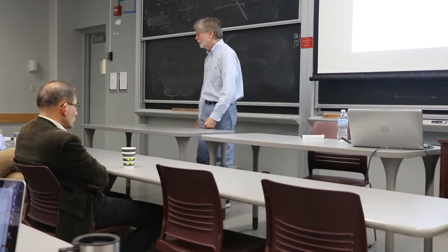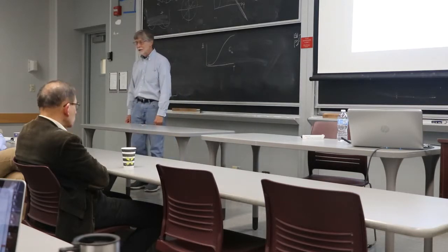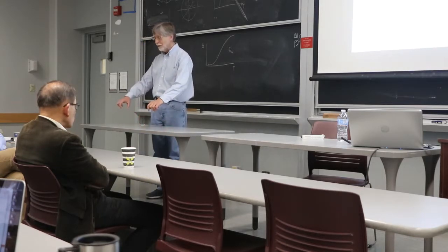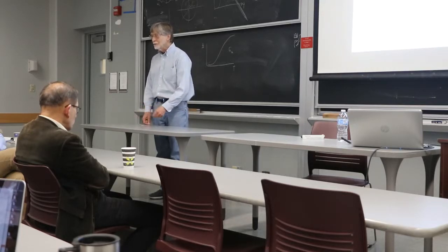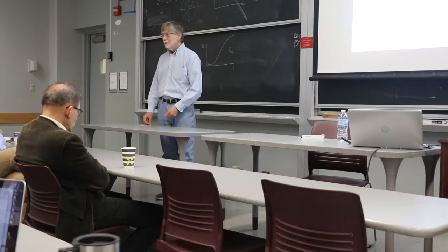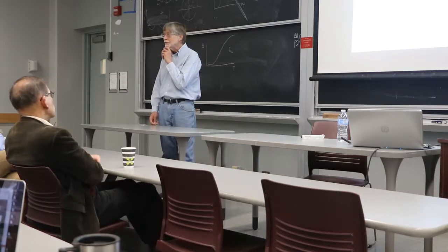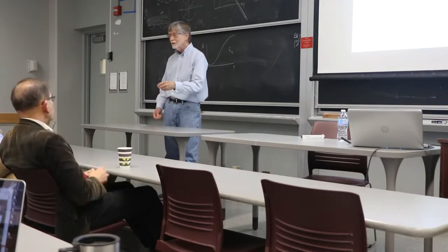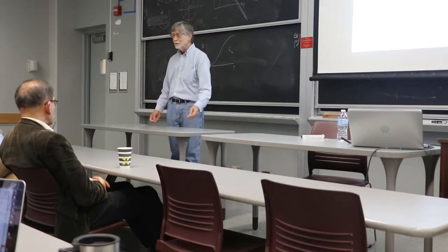Now there's two types, or maybe more, of positron scientists. There's the ones that actually want to do something useful. They can do something useful with 2 little counters, which you can make for a few $100s, and a piece of sodium-22, which costs $60 a millicurie, 6 cents for a microcurie or something. Anyway, nothing. The source is practically free. You take your 2 pieces of material, put them together, measure the lifetime as a function of temperature, and you can tell all sorts of stuff about it.